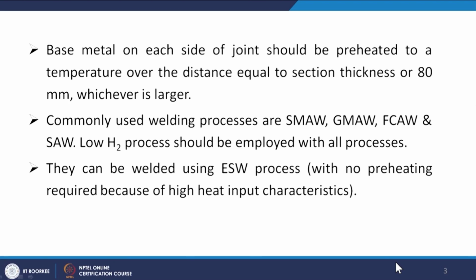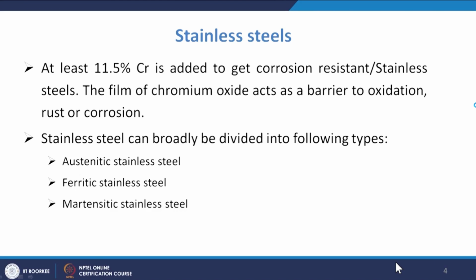The base metal on each side of the joint should be heated to temperature over a distance equal to the section thickness or 80 mm, whichever is larger. Okay. Commonly used welding processes are SMAW, shielded metal arc welding, GMAW, gas metal arc welding, FCAW, flux cored arc welding, SAW, submerged arc welding, and low hydrogen process should be employed with all the processes. Okay, they can be welded using the ESW process, electroslag welding, with no preheat required because of its high heat input characteristics.